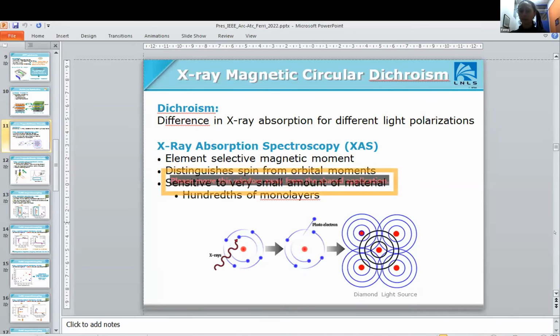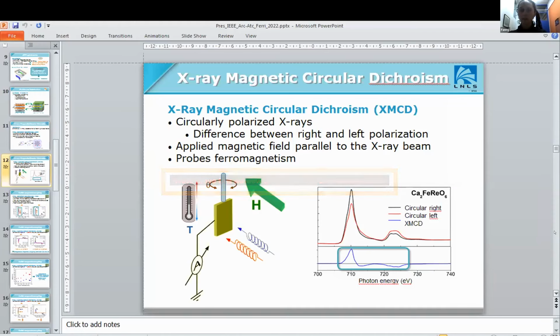So actually we are sending some X-rays, and depending on the energy of the X-ray, you have the emission of photoelectrons, and so basically you have the absorption of the X-ray. Now dichroism will be the difference between two light absorptions that are circularly polarized. One is from the right polarization, the other from the left polarization. You're also applying a magnetic field which is parallel to the X-ray beam, and so you will be able to probe the ferromagnetism of your sample.